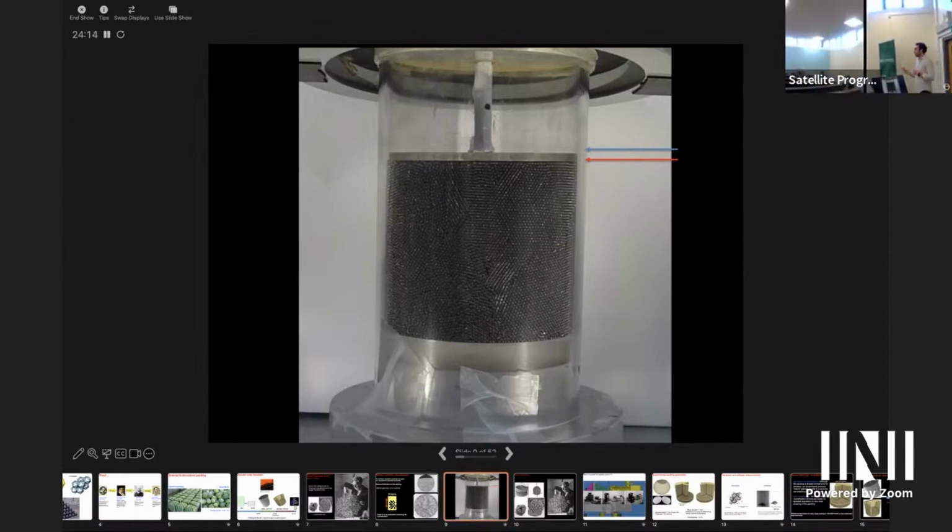Are these highly monodispersed? Monodispersed, yes, they're about 1 millimeter in diameter, and there is a 0.5% polydispersity. And it's better than what we got from the supplier. We found out this really nice low polydispersity later on through tomographic analysis, that they are actually more spherical than they were supposed to be. So yes, it has very low polydispersity. And do acrylic beads deform when they're pushed together? They do to some extent, yes. I will also show you some results on that. Cool.